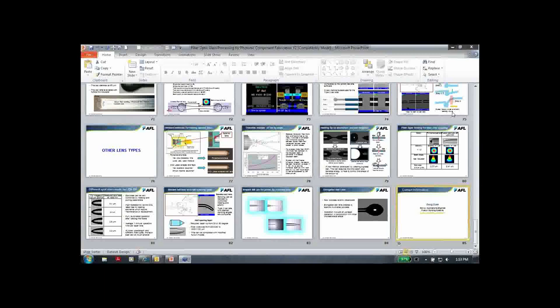For the processes we're using, we have the fiber oriented horizontally, loaded into either a conventional fusion splicer or, in some cases, our LZM, which uses a laser beam. Because we have it oriented horizontally, even with rotation, the largest diameter ratio we're able to achieve right now is about four to one. However, we've just changed our rotational speed capability, so we'll have to re-examine that. We're pretty comfortable with something in the area of three times or four times as big as the original fiber diameter.